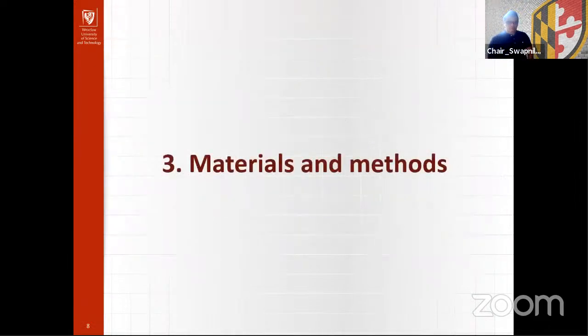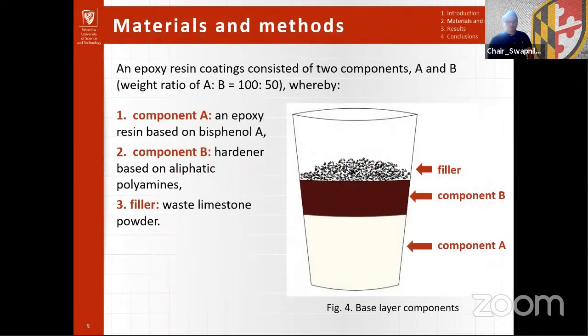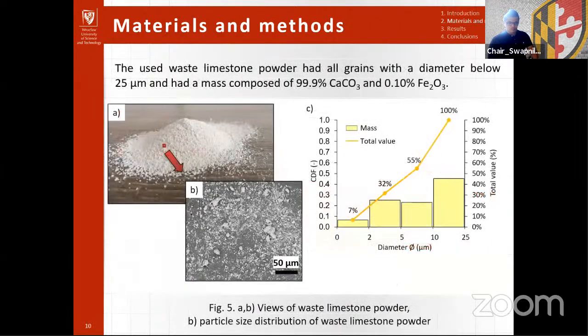Moving to materials and method description. In the research, we used an epoxy resin coating consisting of 2 components, A and B, whereby component A contained an epoxy resin and component B was hardener. We used waste limestone powder as a filler. The used waste limestone powder had all grains with a diameter below 25 micrometers and had a mass composed almost